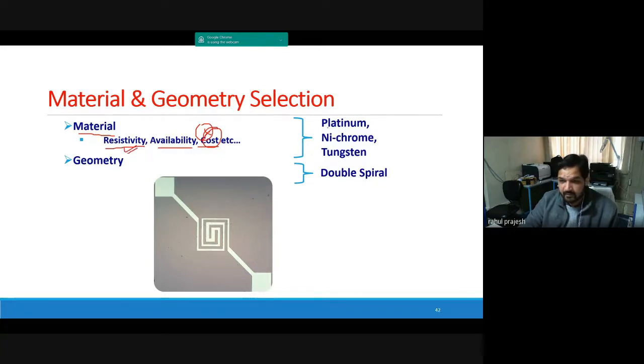So it can be platinum. Platinum is not a very good conductor, so it can be used. Nichrome is also resistive. Tungsten is also resistive. So any material from that can be used. But if you use nichrome, it has tendency to get oxidized. Okay. So if it is oxidized, then now the material is changed. If the material is changed, the resistance is changed. If the resistance is changed, the temperature is changed. Okay. So it's not very stable. But for crude applications, it can be used.